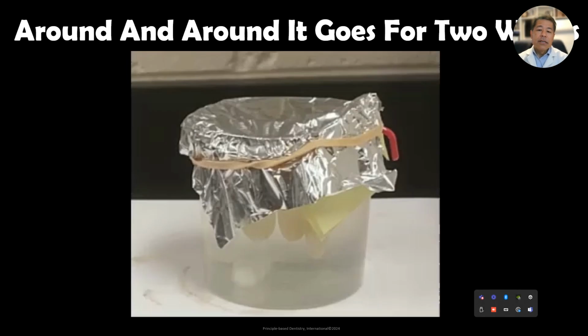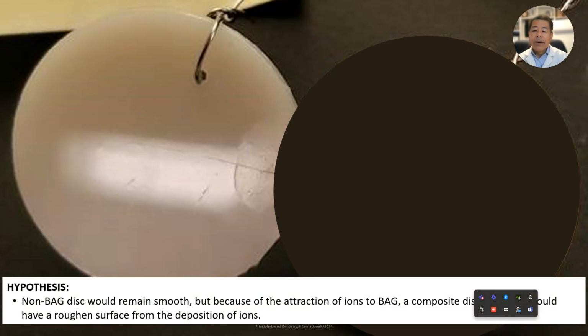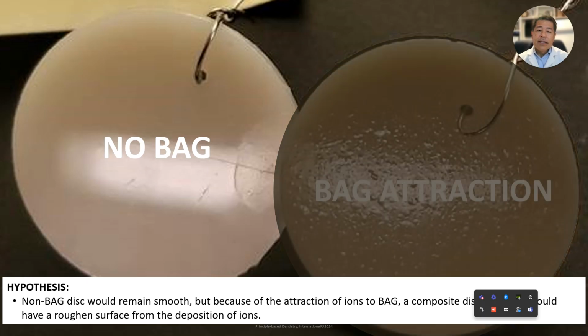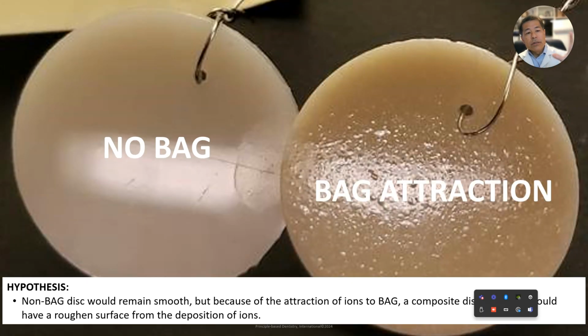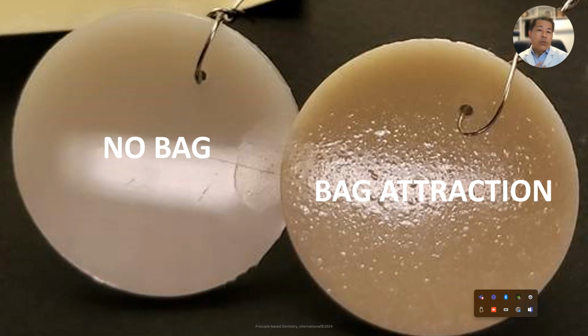So what happened was these composite discs were suspended in this beaker containing artificial saliva, which was stirred for 2 weeks. And at the end of the 2 weeks, you can see on the left-hand side, that is a quarter-size disc of conventional composite, and it remained smooth because there was nothing that would attract calcium and phosphate to that disc. So that's your non-bioactive glass containing disc. On the right hand side, as we unveil this, look what happens. It has this orange peel look to it because the calcium phosphate was attracted to that disc because that disc has bioactive glass in it. So we have that bioactive glass attraction. And imagine if that's your restorative material, what would happen?